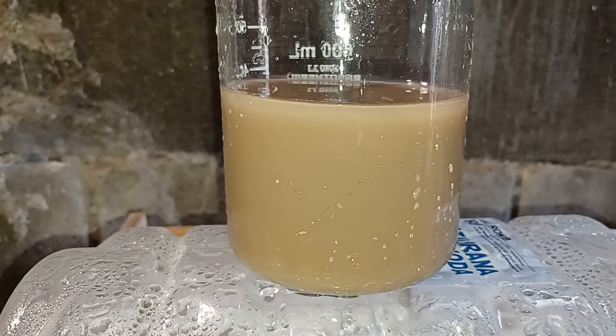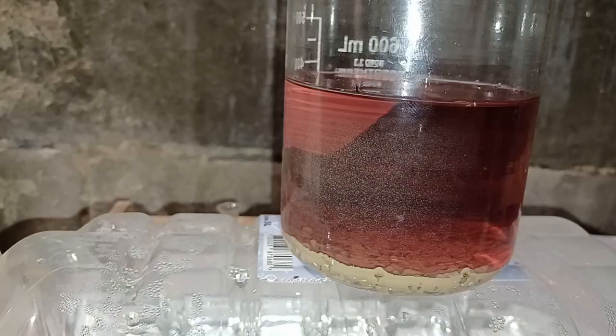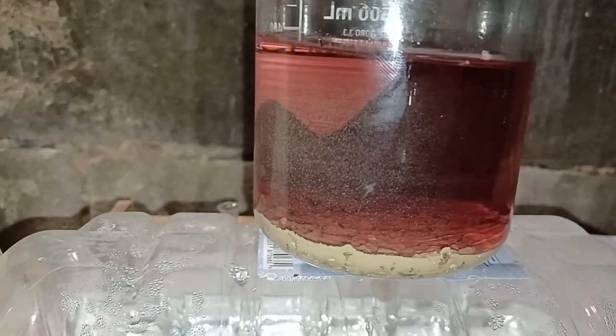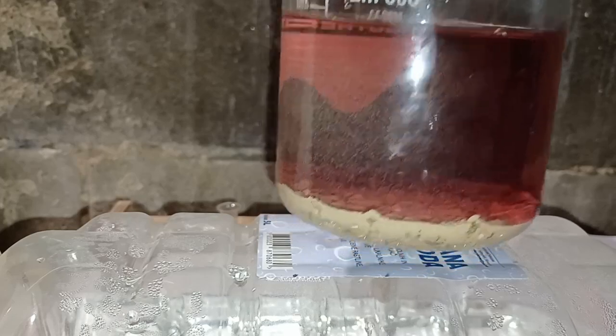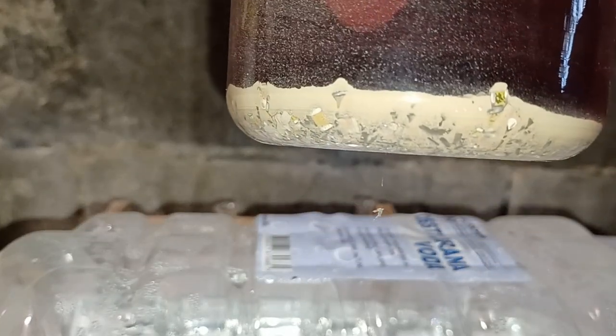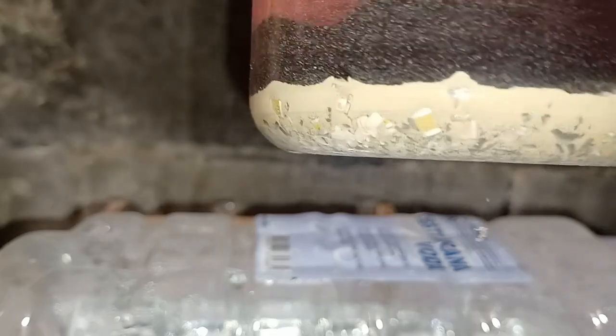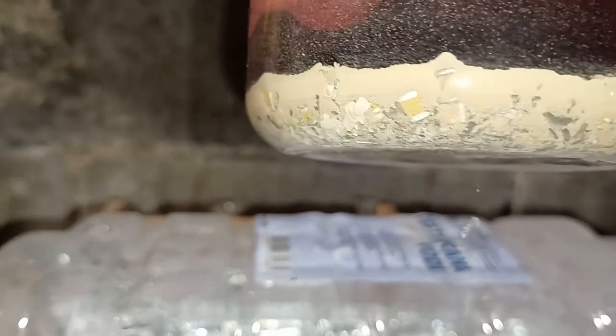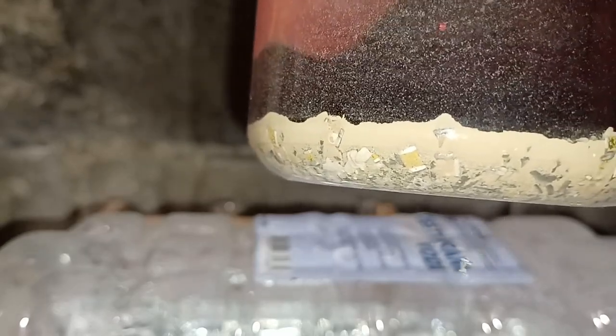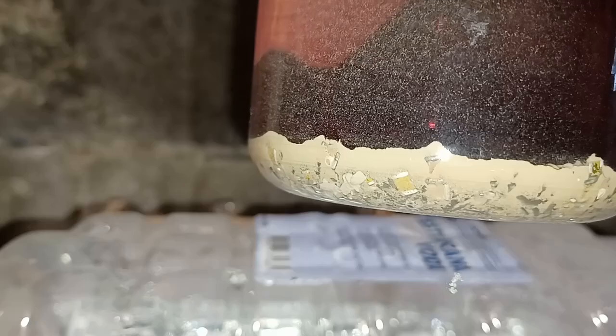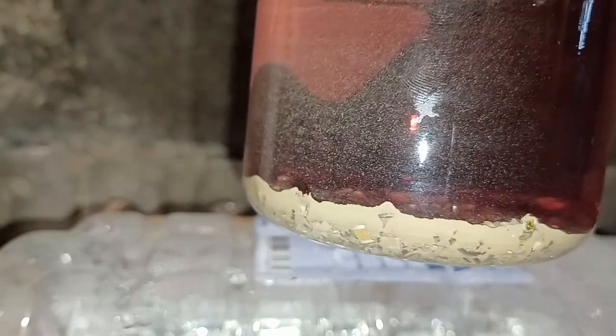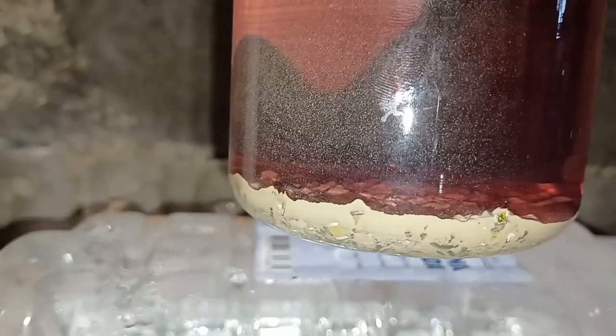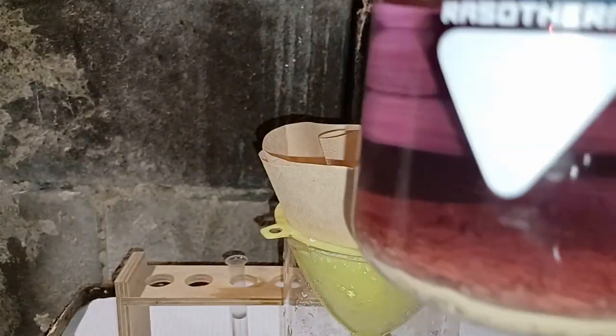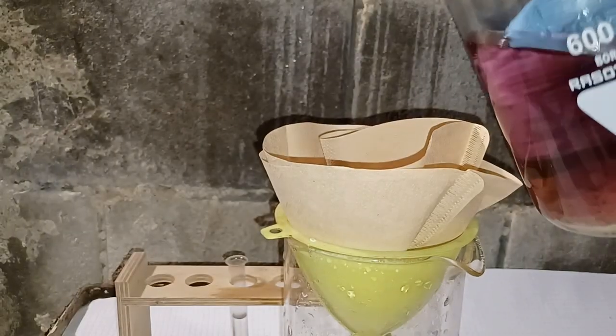After thoroughly stirring it, I left the solution to react for another day. After 2 days, the ceramic fell apart into yellowish powder, and the solution became an even more intense reddish color. While the color is strongly reminiscent of palladium chloride, only a very small amount of it should be present in solution. I believe the color is due to a mix of cobalt, nickel and manganese chlorides. After I was done dissolving the ceramic,